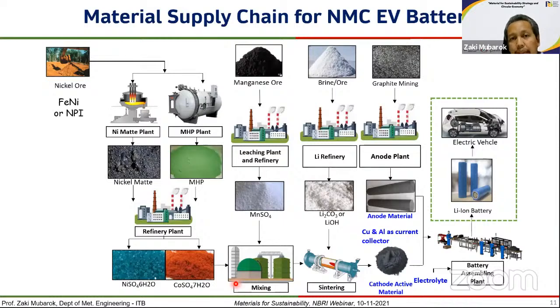Okay, I think if we take a look at the material supply chains for NMC battery, the nickel sulfate and cobalt sulfate can be provided from extraction of nickel laterite ore, also from the existing nickel matte plant, and we also need manganese sulfate, graphite, and lithium. Lithium carbonate or lithium hydroxide is mixed, as I have mentioned before, with nickel sulfate, cobalt sulfate, manganese sulfate to produce then precursor cathode material and to establish the cell battery and for electric vehicle.